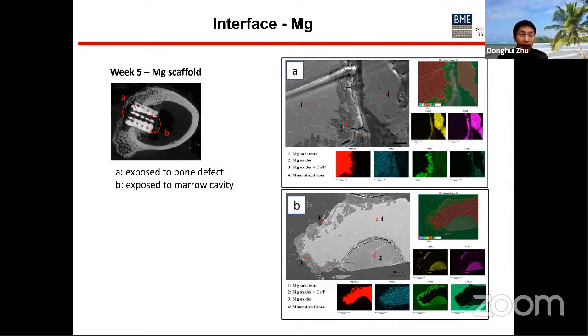At region A, the oxide layer is relatively homogeneous and relatively thin, while in the cavity region, the degradation behavior is stronger with a thick or different type of degradation product layer, including magnesium oxide, calcium phosphate compound, and also some mineralized bone product.